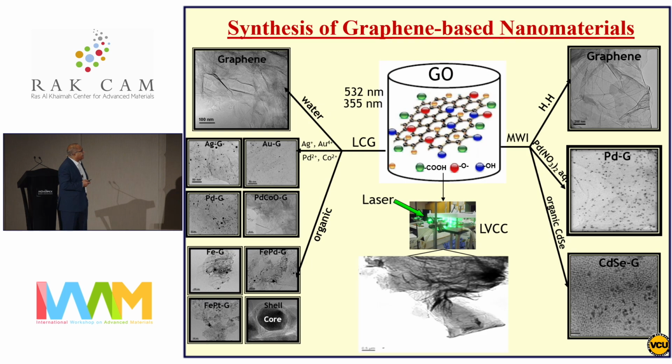So for our first way to do this, of course, it's very easy and straightforward to make graphene oxide from graphite by the Hummers method, which is a very well developed method. The graphene oxide is characterized by separate sheets that are well dispersed in water. Then we take this graphene oxide solution with a metal ion, the palladium salt, and we undergo two types of process.